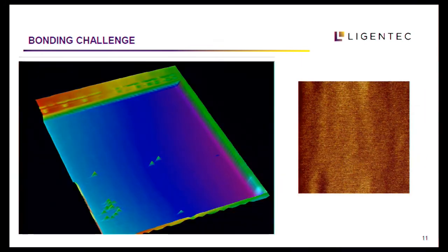Now, the challenges of this one is, as you can see in this image, these green waves are actually particles. So we had contamination on this specific chip. This means that if you try to put a material here, these particles are going to break your material, and you are going to have a loss. It will not work, so both chips are going to be lost. And this is an AFM image that I just want to show that you need to be really flat and really uniform. So you can probably get a bonding with a 2 nanometer RMS, but ideally you want to be lower than that.